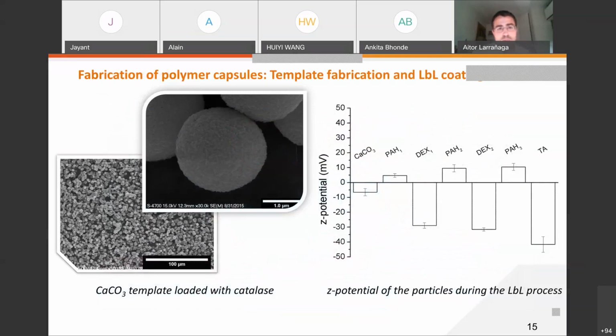So in these scanning electron micrographs, you can see how the calcium carbonate template loaded with catalase looks like. As you can see, they are spherical, highly porous particles with a diameter between 2 and 3 microns. The initial surface charge of these particles was negative due to the entrapment of the catalase inside. So then we proceed with the layer-by-layer approach. And as we expected, the zeta potential, the surface charge of our particles, was changing from positive to negative as we were incubating these particles with positively or negatively charged polyelectrolytes.